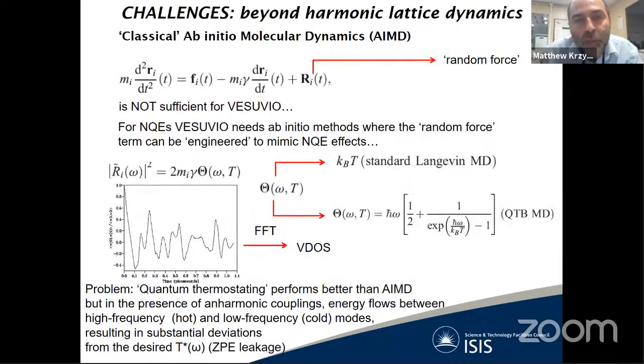Nevertheless, obviously there are challenges beyond harmonic lattice dynamics. One of them is to predict the exact shape of nuclear momentum distributions that cannot sometimes be elucidated from harmonic lattice dynamics. And what comes to the rescue here is the existence of sophisticated methods of ab initio molecular dynamics, especially those that use quantum thermostating for the description of the coupling of the random force to the environment. The chief idea here is to mimic the quantumness of the nuclear degrees of freedom by using the generalized Langevin equation, which has the property that the spectral density of the autocorrelation function of the random force exhibits the same shape in frequency as the spectral density of the excitations of the quantum harmonic oscillator.